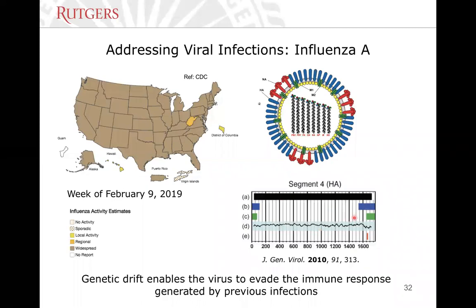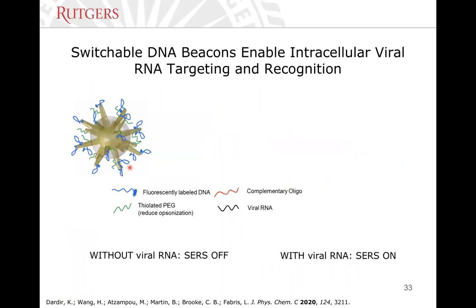So what we told ourselves, well, if we target these conserved regions, we will always be able to pinpoint and quantify a virus wherever it is. And so what we did was to design gold nanostars. We partially coated them with silica because we saw that it can enhance the signal while providing stability. We functionalized them with PEG for biocompatibility, and also we functionalized them with this oligonucleotide with DNA that is